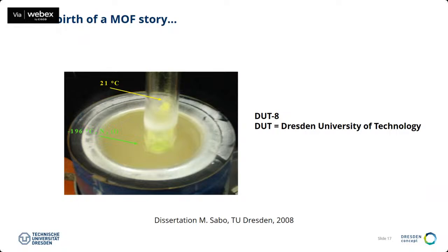but when I put it in liquid nitrogen, it changes the color. So the upper part of the sample, which is still warm, is yellow. And here the colors are maybe a bit difficult to see, but at this low temperature, it is green." And it was totally strange. At that time, we could not do X-ray diffraction at these low temperatures, and we did not understand anything. But it was this observation that triggered a lot of new studies on this kind of material.